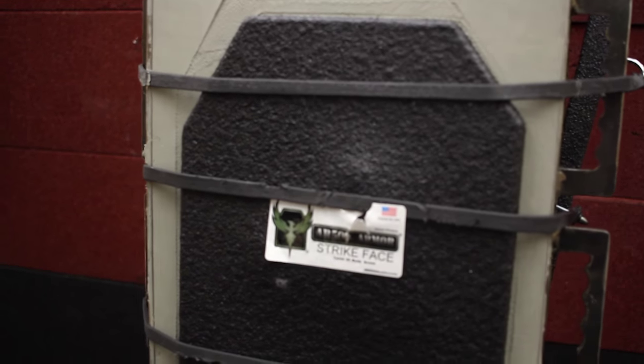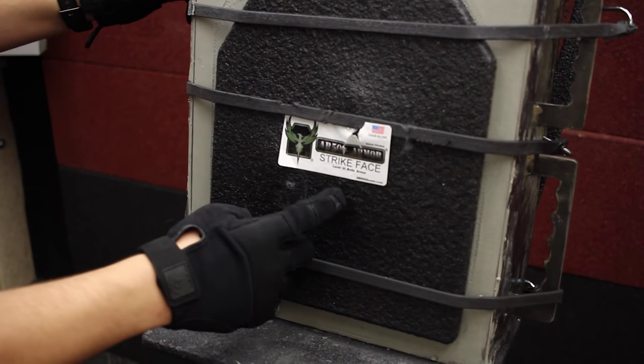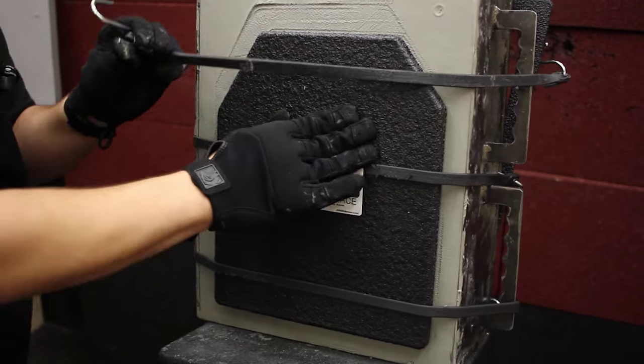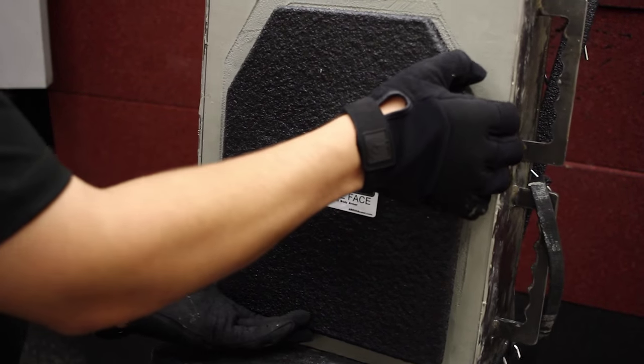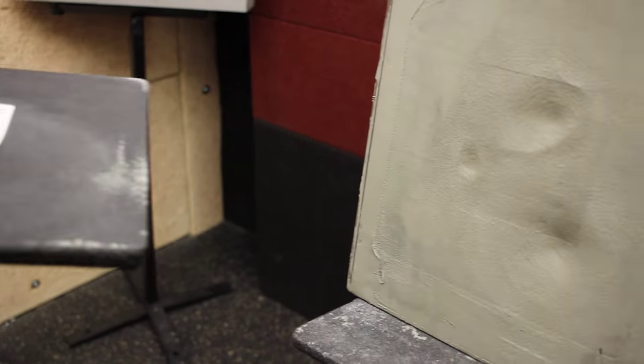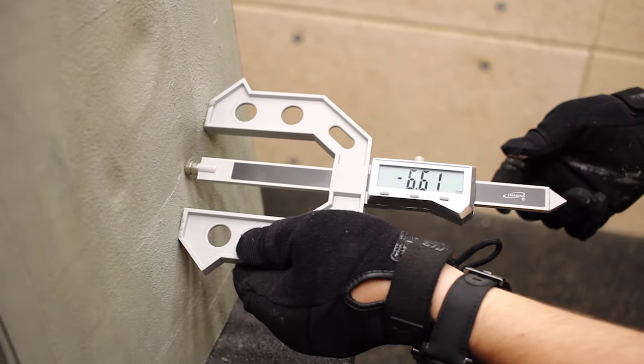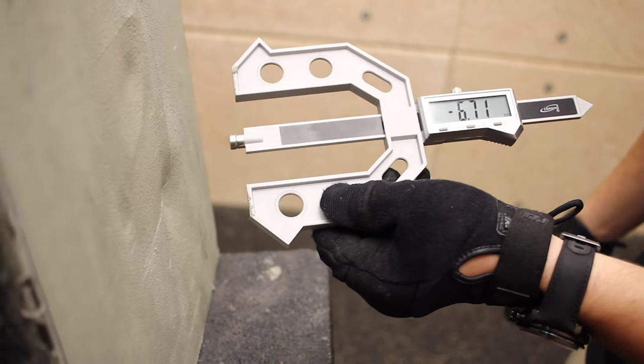Let's take a look. It looks like we impacted right there. No penetration — the plate still looks very good. Let's grab our depth micrometer and see where we ended up. We have our depth micrometer zeroed out. Let's get the deepest part possible — we're at about 6.71mm of back face deformation. You can tell that one was traveling with a little bit more energy, but we are still well under the 44mm threshold set by NIJ 06 standards.